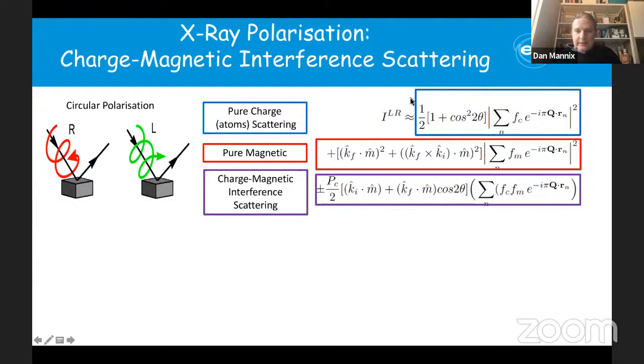And in fact, the charge scattering terms can be isolated if I just take the sum. By using circular light on these, looking at Bragg peaks, and this is important to express now, the Bragg peaks that we are looking at in these ferromagnetic systems consist of both magnetic and charge scattering. So they both contribute to the same Bragg peak. The idea is we want to actually separate out the magnetic scattering from the charge scattering. And the way in which we do that is using this interference scattering, which is related to that scattering strength, not just the pure magnetic one.